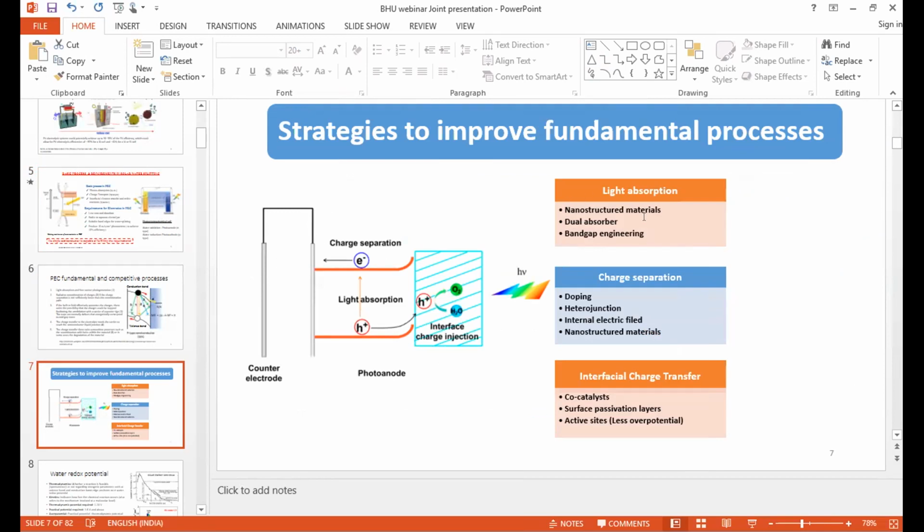So we haven't actually started any kind of nanostructure, but normally if you have wires or rods, when light is illuminated on such a structure, the light can get scattered multiple times. This multiple scattering of light will eventually lead to more prolonged optical interaction with the material, and thereby enhanced absorption, compared to if you just take a flat thin film.